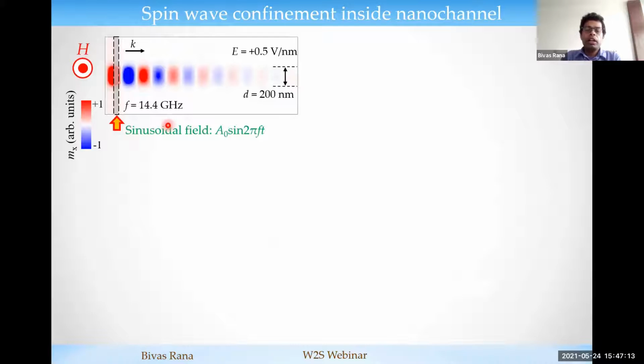Here is some micromagnetic simulation I performed to show this. We have a waveguide with 800 nanometer width and 2 micrometer length, and we try to excite the spin wave by applying a sinusoidal magnetic field within this dotted shaded line. Okay, then interestingly you can see the spin waves are strictly confined within this channel having a width of 200 nanometers.